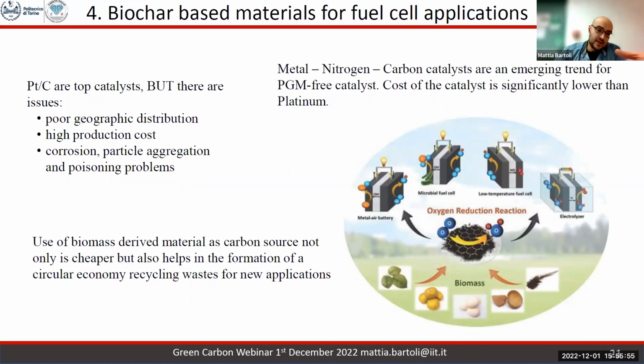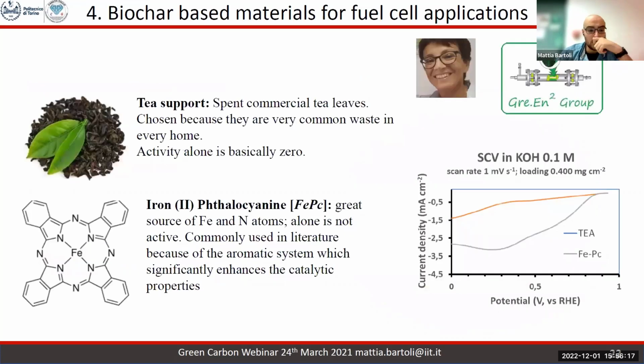The problem is, as you can figure, that platinum supported on carbon black mainly, or graphene, reduced graphene, are quite effective in this kind of electrocatalysis routes. So we tried to engineer biochar to match the properties. It was a difficult challenge. With the collaboration of Professoressa Stefania Specchia from Green Energy Group of Politecnico of Turin, we try to combine biochar